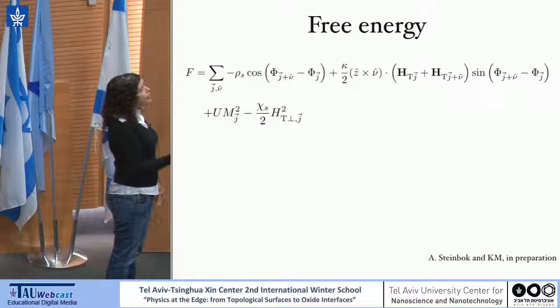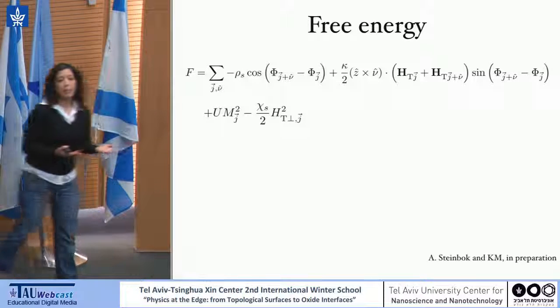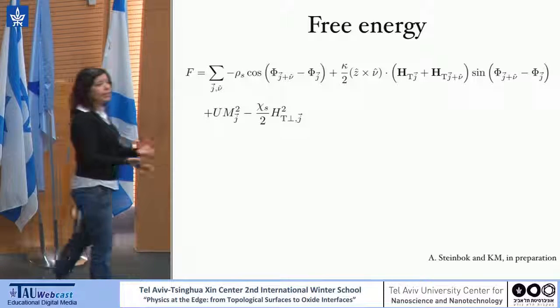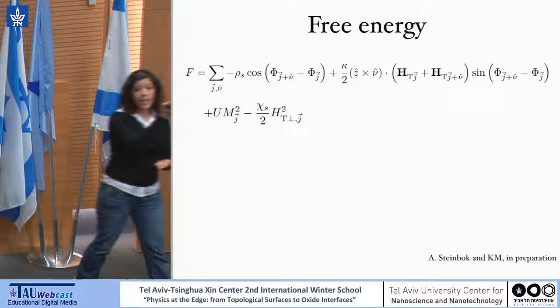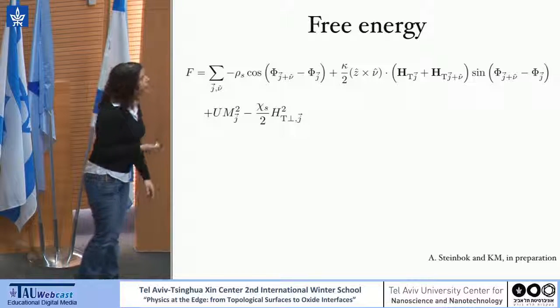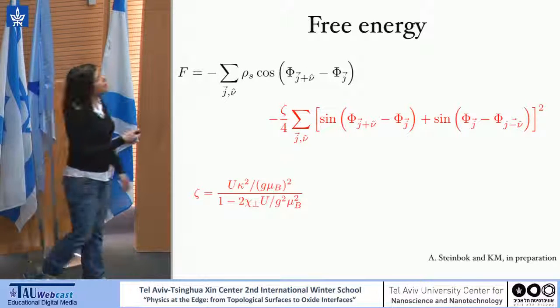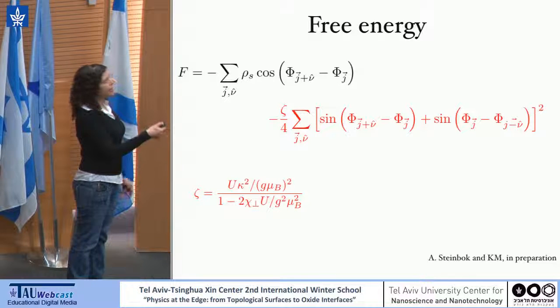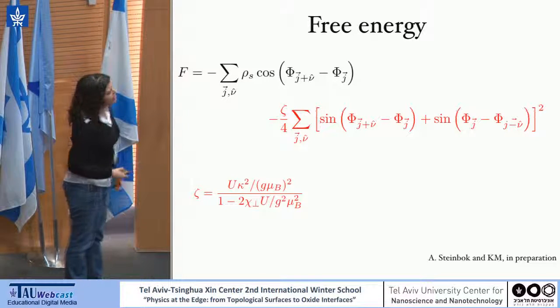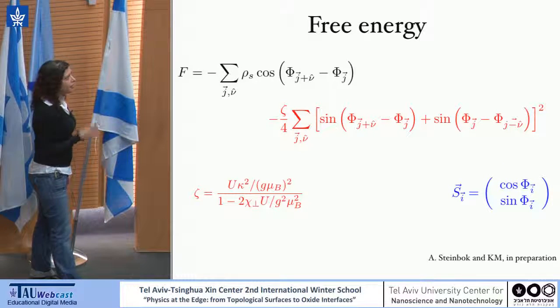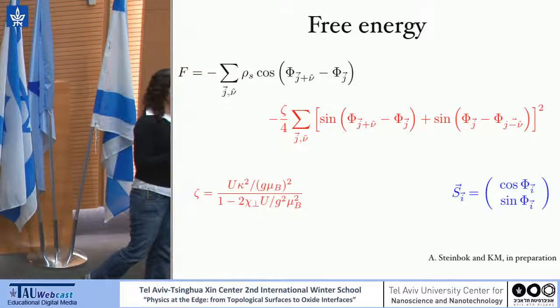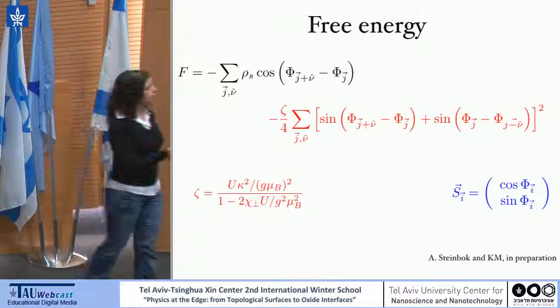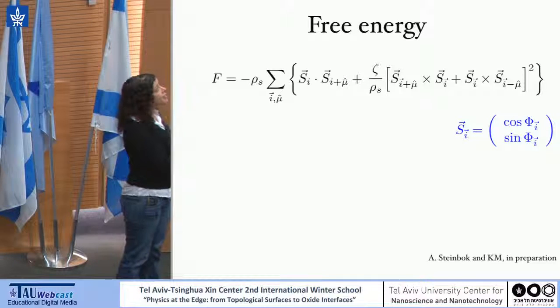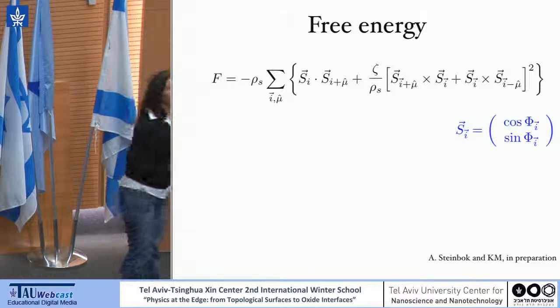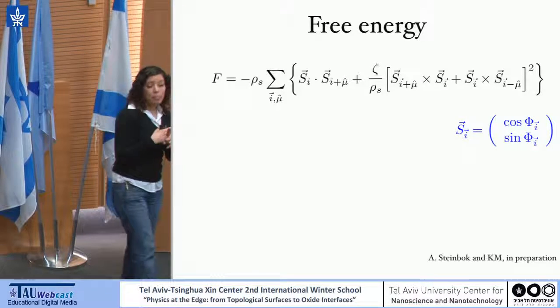We will be back in our free energy and ask what happens if we have fluctuation in the magnetization. So we are in the vicinity, but still in the non-magnetic state, but we have quite strong magnetic fluctuation. And we will integrate them out. And what we will get is that we have the regular phase stiffness term and an additional term that looks maybe a bit complicated, but if you will let me write our phase as some kind of xy spin, then this term looks like basically a ferromagnetic interaction between neighboring spins and some kind of angle-dependent interaction between spins.